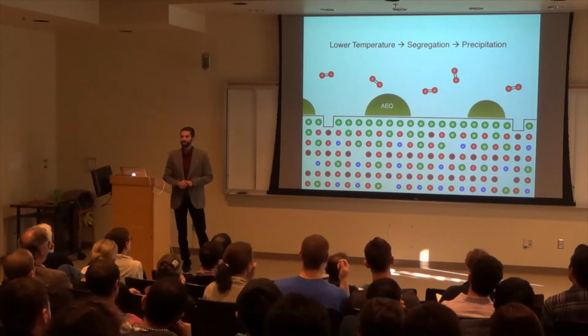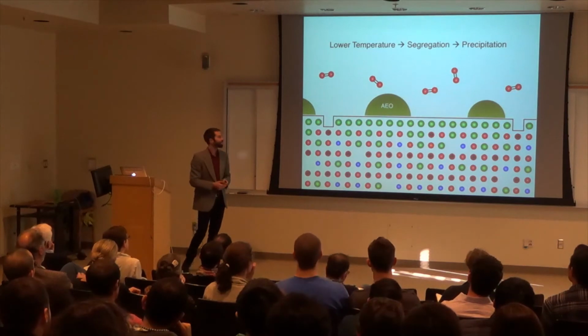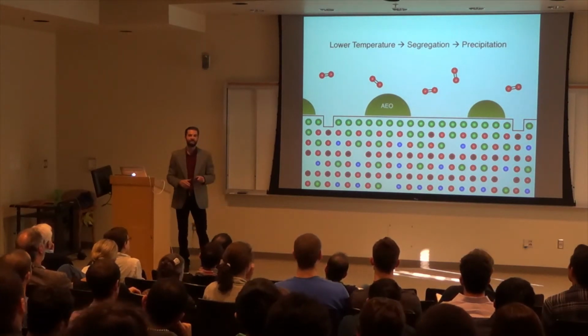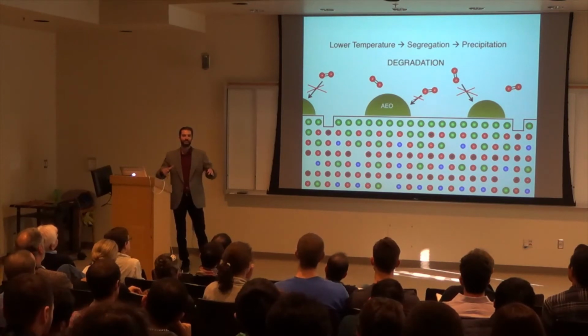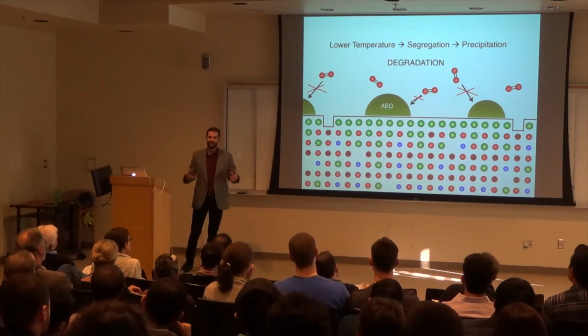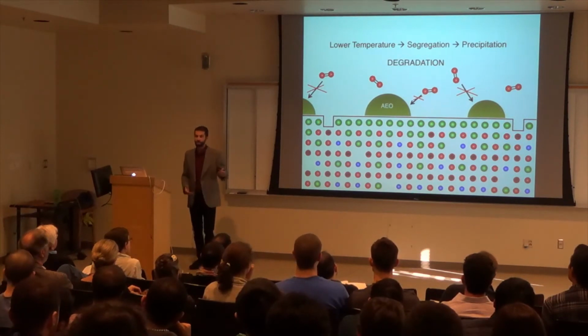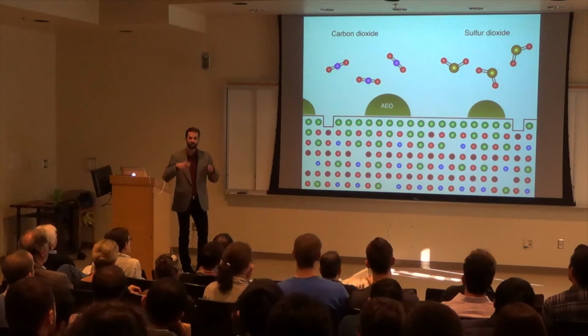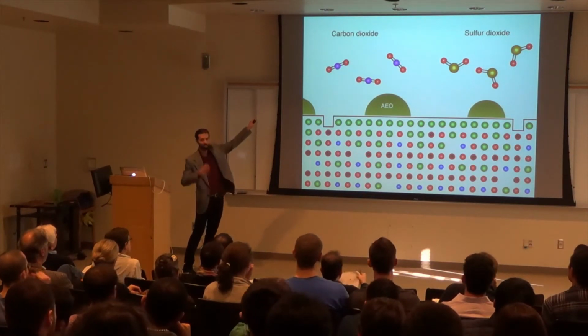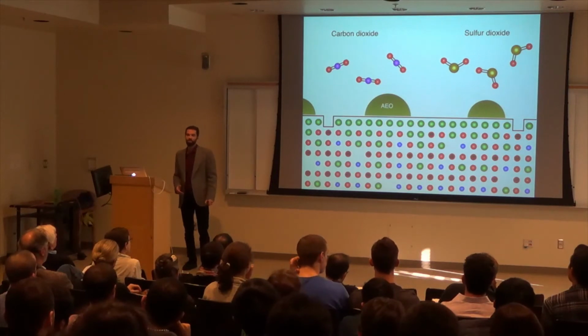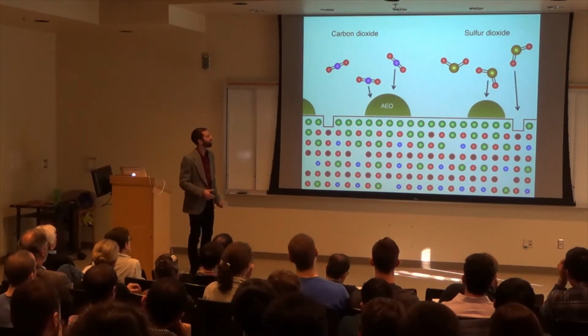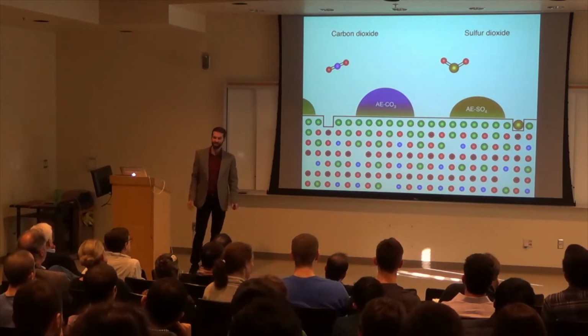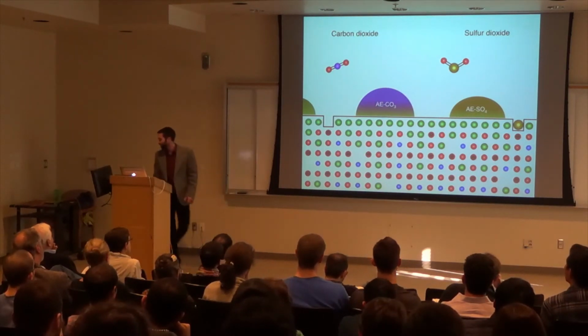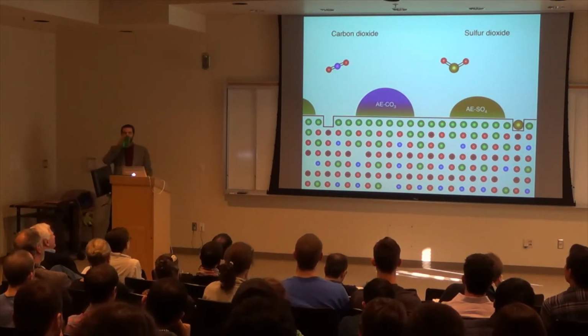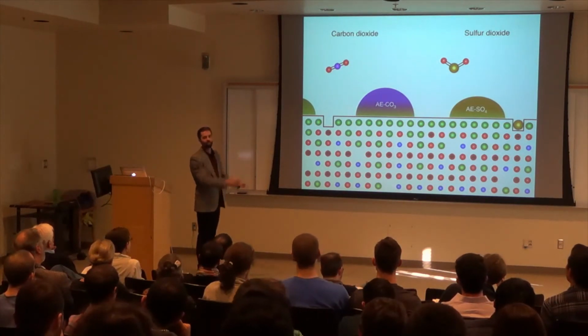Now, precipitation is considered to be a bad thing in this area of research, where these precipitates, these islands, are thought to be catalytically inactive and blocking, so that you essentially passivate the surface so that it can't react so much with the oxygen gas. Further, under real conditions, as opposed to ones where you have a very controlled gas, in the air that we breathe, we have carbon dioxide and sulfur dioxide. Now these can react further with the precipitates, further passivating the surface and essentially killing the catalytic activity of the material. So the motivation for the study I'm about to tell you about is to try to understand what can we do to understand this process that's going on here.